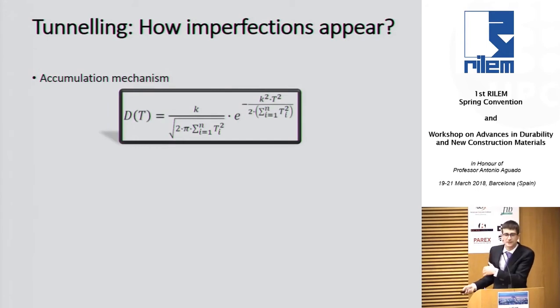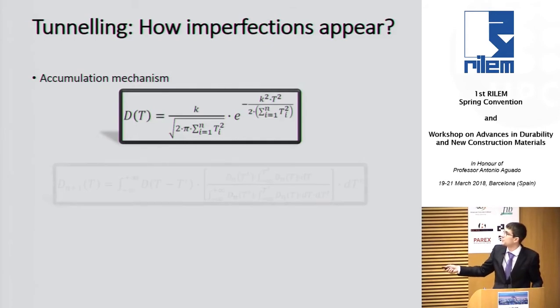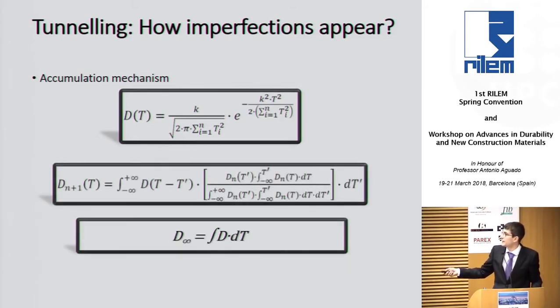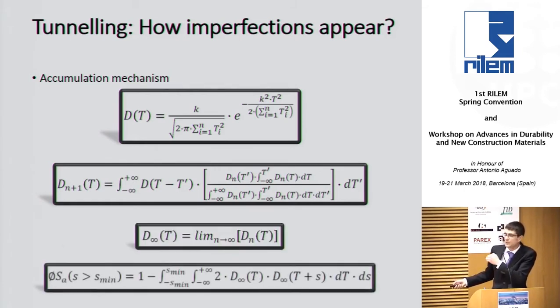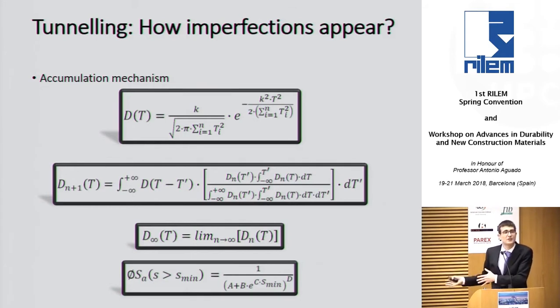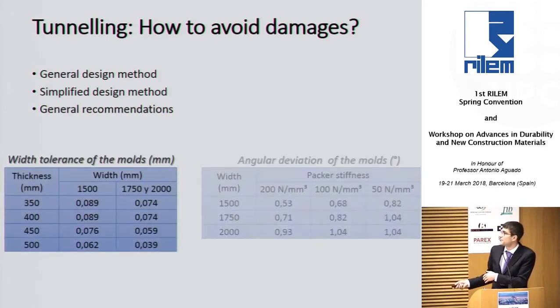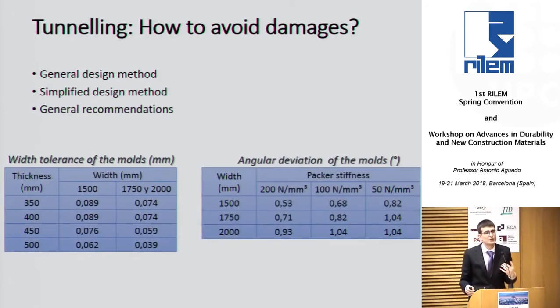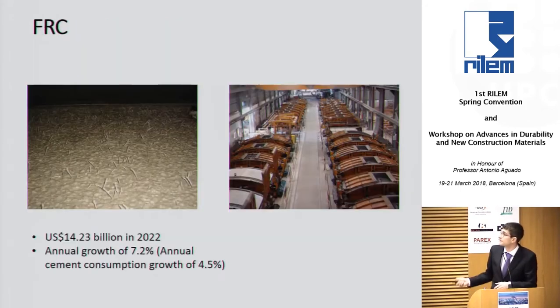So we had to develop several relatively complex equations, starting with probability distributions sums, and then integrals of many rings being placed together, integrating the probability, and arriving to what we thought were simplified equations, which were complex even for application. But at the end, general recommendations on how to consider these tolerances and how to define if a segment is acceptable or not acceptable. So this was an interesting contribution for reducing the frequency of these damages, right?